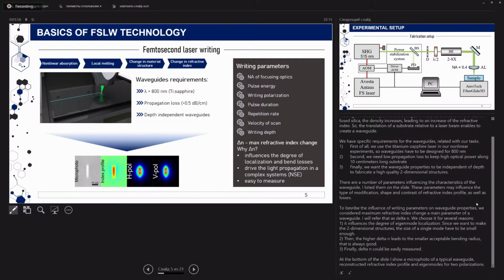It influences the degree of eigenmode localization, since we want to make two-dimensional structures, the size of a single mode has to be small enough. Then the higher delta n leads to the smaller acceptable bending radius, and that is always good. And finally, delta n could be easily measured. At the bottom of the slide, I show a micro photo of a typical waveguide, a reconstructed refractive index profile, and eigenmodes for two polarizations.